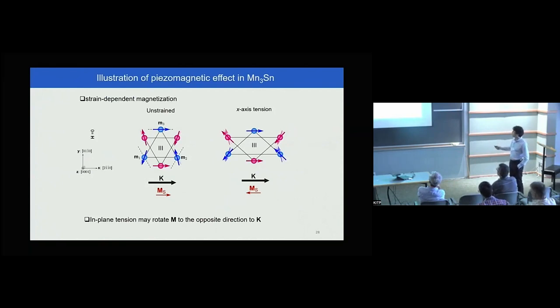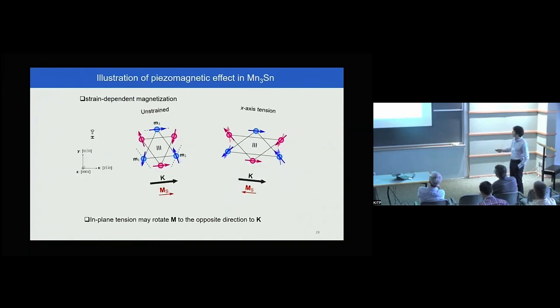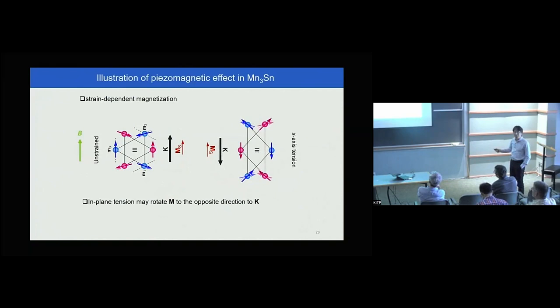So under the magnetic field, you should be able to align magnetization, of course. So what you actually expect is the change of this octopolar state. In other words, you should be able to switch your spin direction by 180 degrees. And if this is the case, and if the anomalous Hall effect is dictated by octopolar direction, you should be able to see the sign change of the anomalous Hall effect. So let's see whether this works.